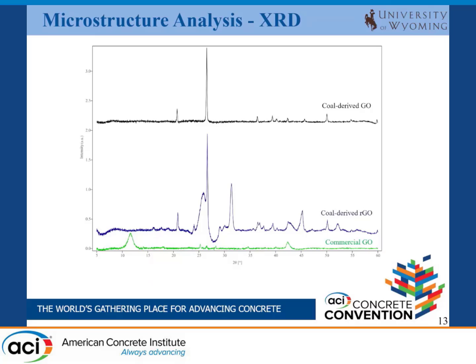We did some XRD analysis to find the crystalline properties of our graphene oxide and the commercial graphene oxide. If you see the peak intensity, the D spacing, and the peak position, there are lots of differences between our graphene oxide and the commercial graphene oxide. The high peak intensity and the low D spacing indicate that our graphene oxide has more crystalline phase and a more stable phase than the commercial graphene oxide.